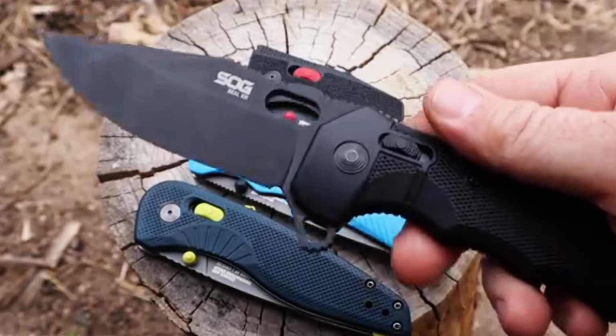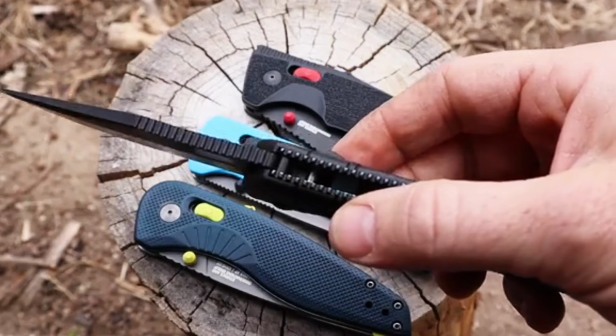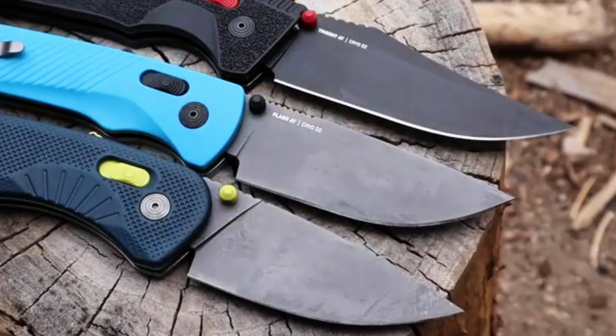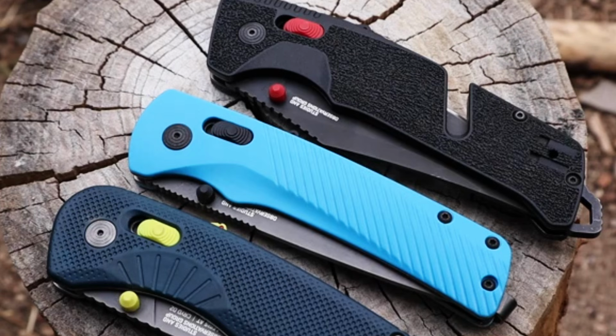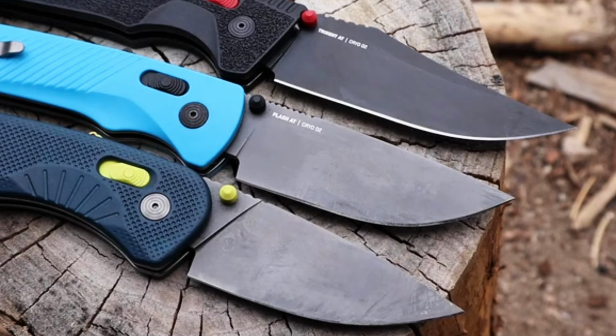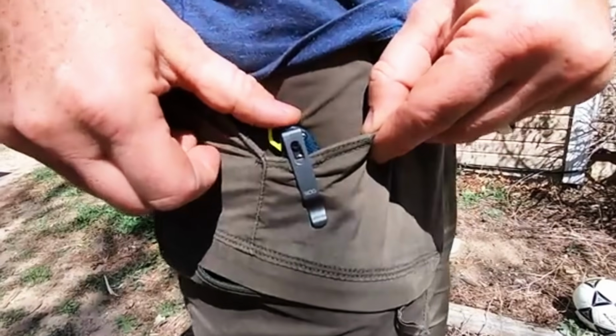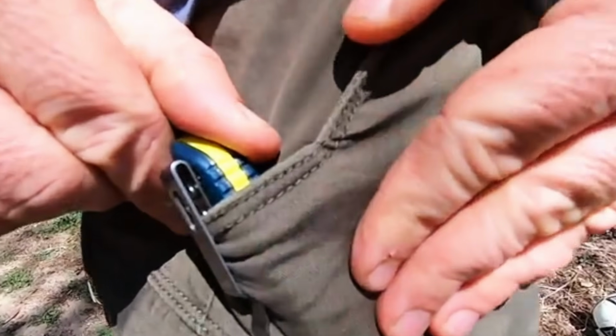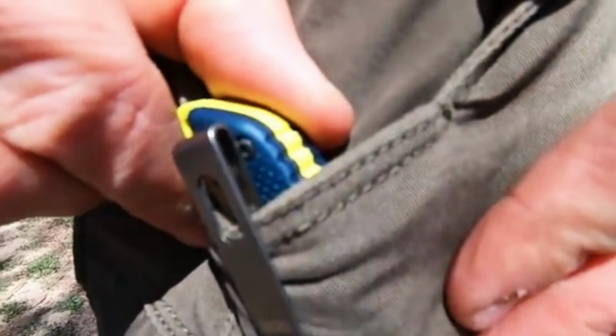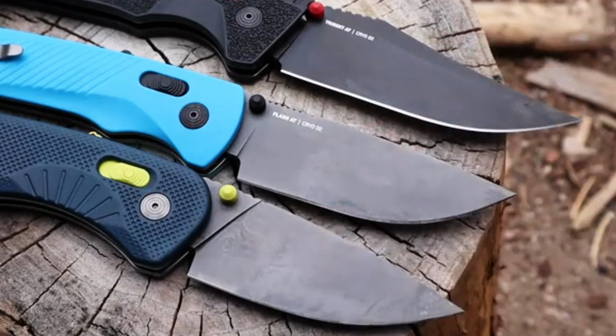D2's high hardness and large carbide structure make it significantly more prone to chipping under lateral stress than either 1095 or S35VN. In my batoning tests on knotted hardwood, the D2 blade showed micro-chipping in exactly the situations where you most need the knife to hold together: hard lateral impacts on grain changes and knots. Micro-chips do not resharpen with a field stone. They require grinding on a coarse abrasive, which is not a realistic field repair.